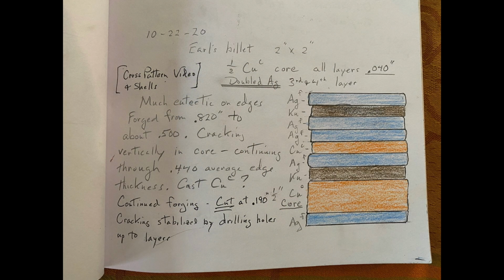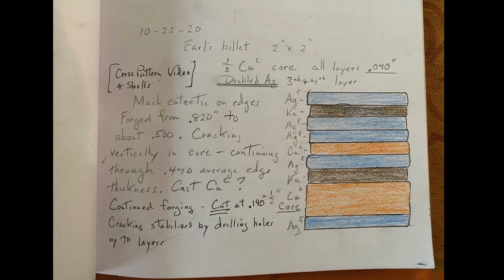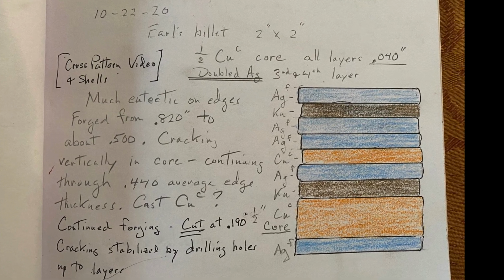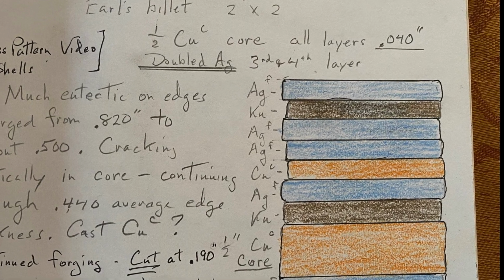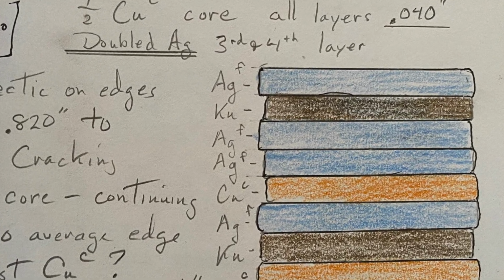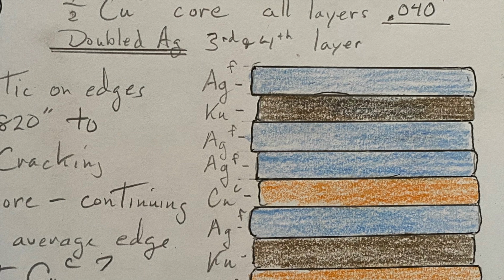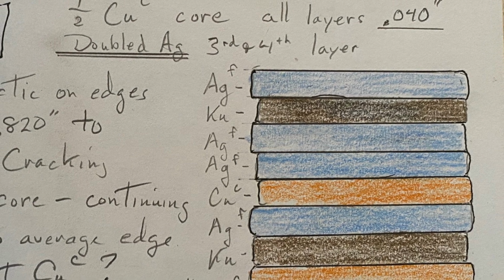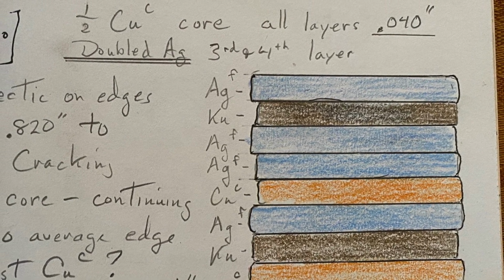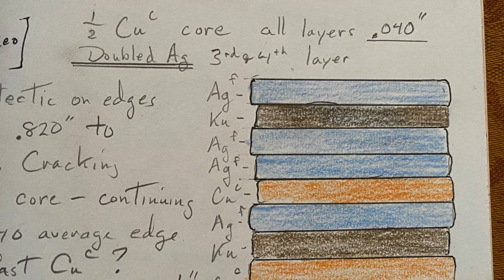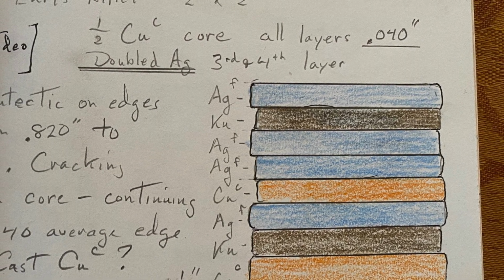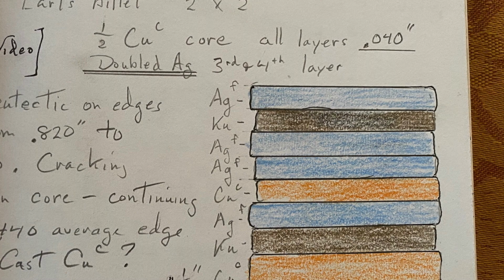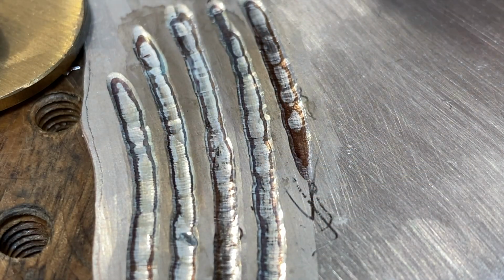Here is a diagram of this billet from my notebook. That extra thick 3rd layer of silver is actually 2 fused layers of fine silver. That's that little F superscript. The KU on the 2nd layer down tells me that I use kuromido alloy here. It'll patinate really black or dark brown and make a good contrast next to the silver.